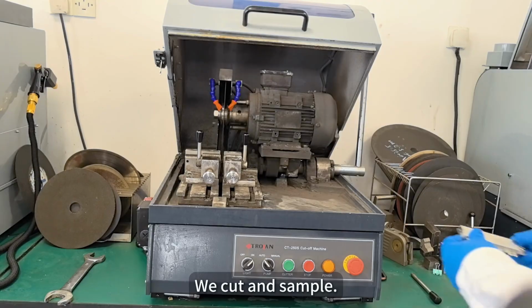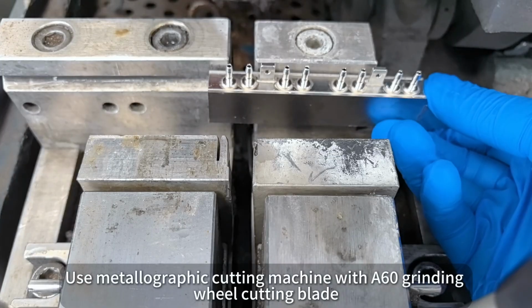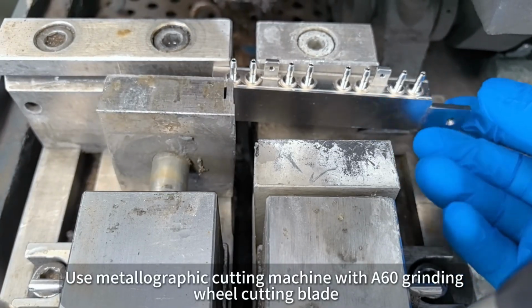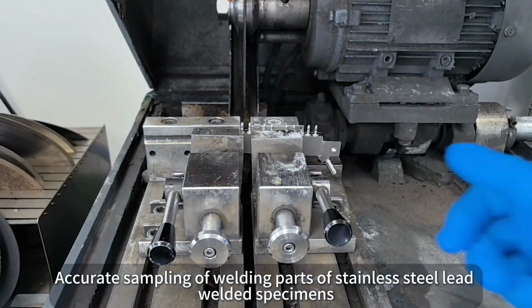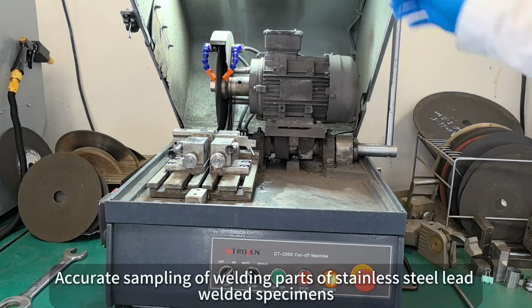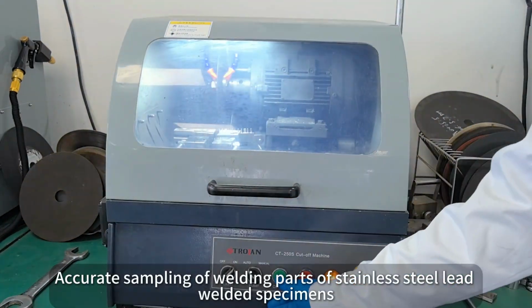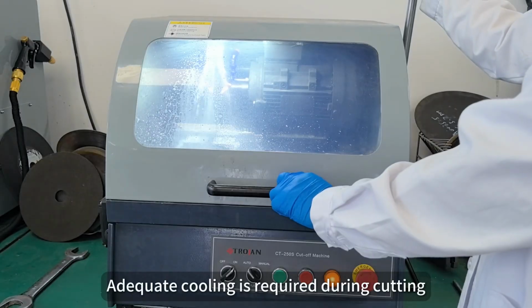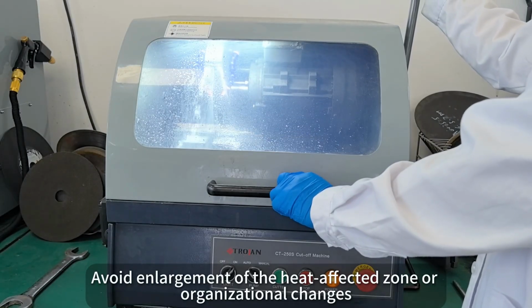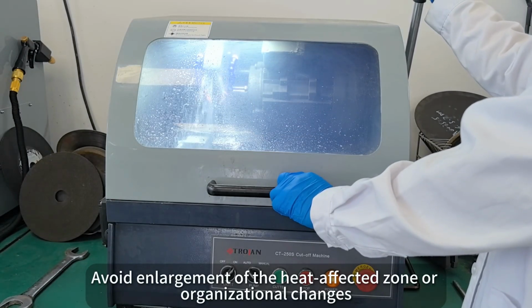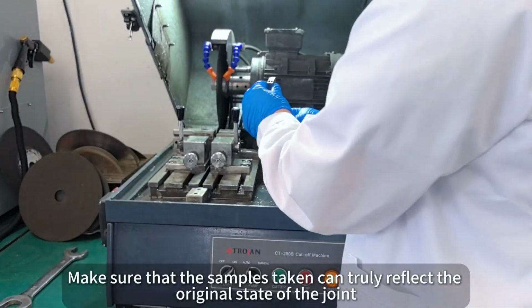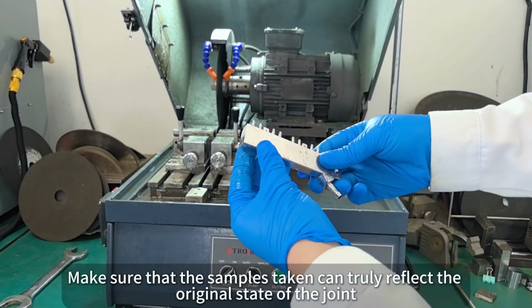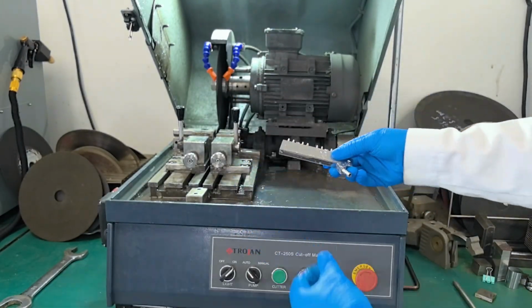Cutting. We cut and sample. Use a metallographic cutting machine with an A60 grinding wheel cutting blade. Accurately sample the welded parts of the stainless steel welded specimens. Adequate cooling is required during cutting to avoid enlargement of the heat-affected zone or microstructural changes. Make sure that the samples taken can truly reflect the original state of the joint.